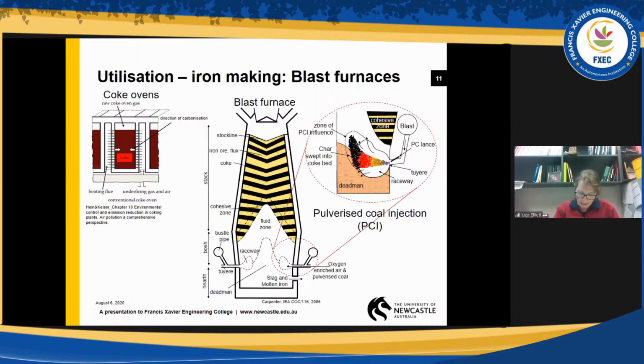So, okay, the issues that we have here in terms of PCI, so I should just mention PCI, the coal that goes into there will experience very, very fast heating rates. We're talking about 10 to the 5 to 10 to the 6 degrees per second. It will also experience very high temperatures. We're talking about 2,200 degrees in the raceway area. So the coal that goes in there, if it's not reactive enough, because it's only got about 20 milliseconds to get across that raceway, if it's not reactive enough,